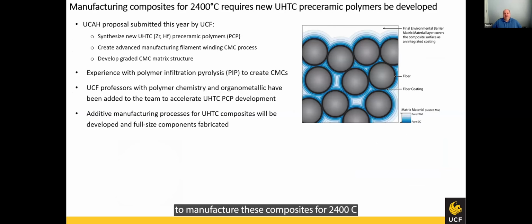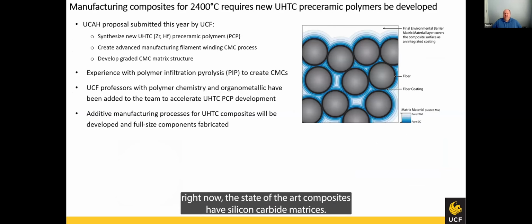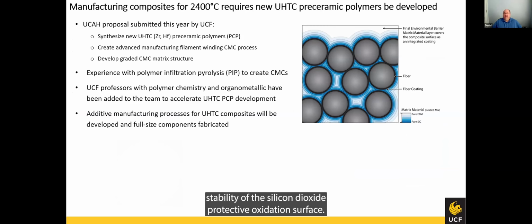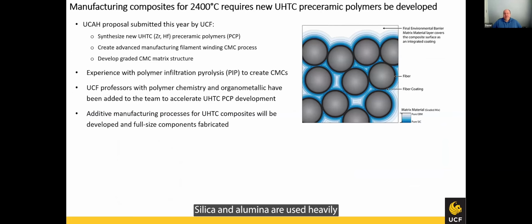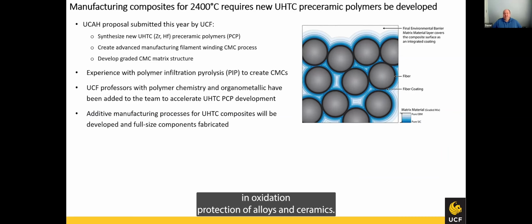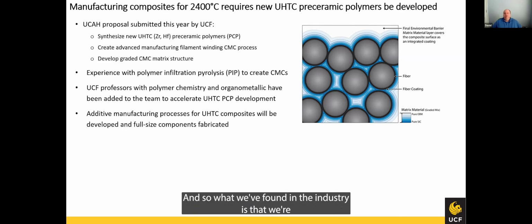So in order to manufacture these composites for 2400 C, right now the state-of-the-art composites have silicon carbide matrices. Silicon carbide is limited to 1750 C based on the stability of the silicon dioxide protective oxidation surface. Silica and alumina are used heavily in oxidation protection of alloys and ceramics. However, at about 1750 C, they start vaporizing and they're no longer protective. And so what we found in the industry is that we're just going to have multi-materials and UHTCs. So we're going to have to start mixing up things.